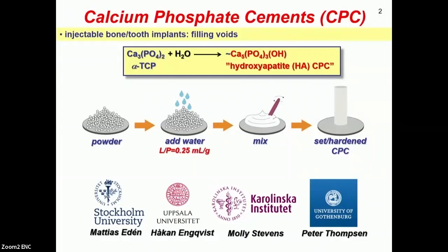Calcium phosphate cements are used as biomedical implants, particularly for filling voids in bone and tooth. And one well-known cement is formed by taking a powder of alpha tricalcium phosphate, mix it with water, and then this paste sets and hardens into a structurally disordered form of hydroxyapatite, which has a similar chemical composition to bone mineral. What I want to talk about today concerns phosphoserine-doped cements.